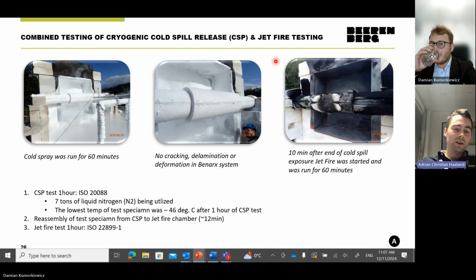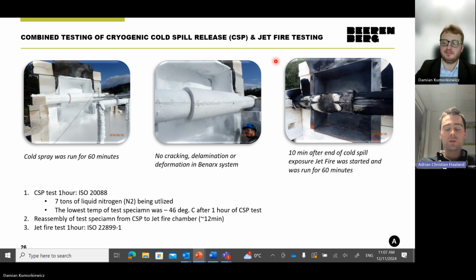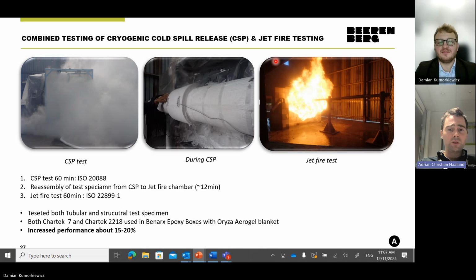So after the cloud clears up, you put this test specimen straight into the jet fire. You inspect that nothing is cracked, everything is still in place, no damage. You do the jet fire, and if you pass, then you are tested and verified against this combined scenario. The purpose of this CSP testing is actually to simulate the effect of liquid natural gas release onto the process area, which I will come back to a little bit later.